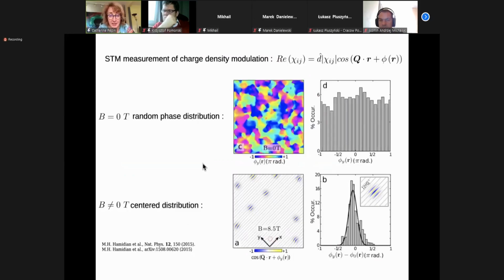Here is another recent STM experiment, which is quite unusual. Here is a phase slip of the charge modulation that you can see over there, with a phase depending on R. They see this distribution at 4 Kelvin, inside the superconducting phase. There is superposition and coexistence between superconductivity and charge modulation. And you see the distribution of phase is super random, going from -1 to 1.